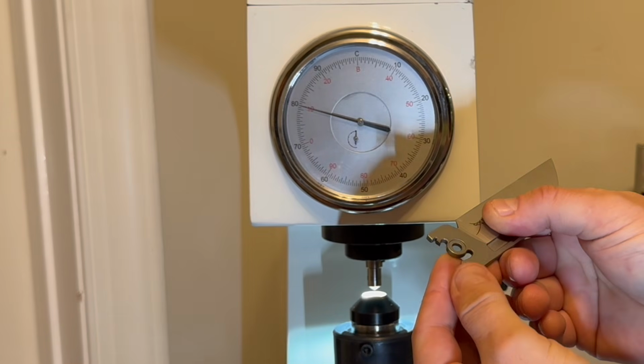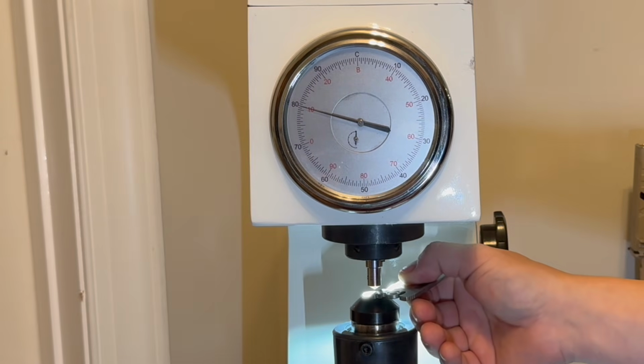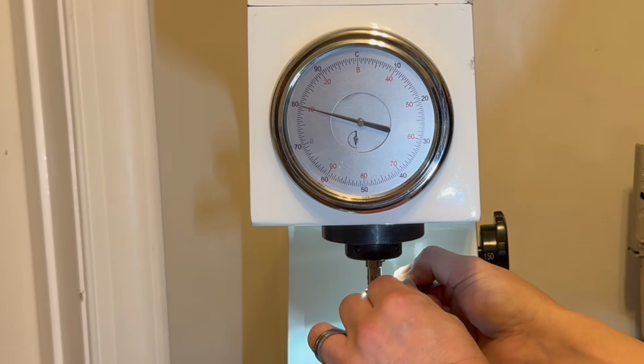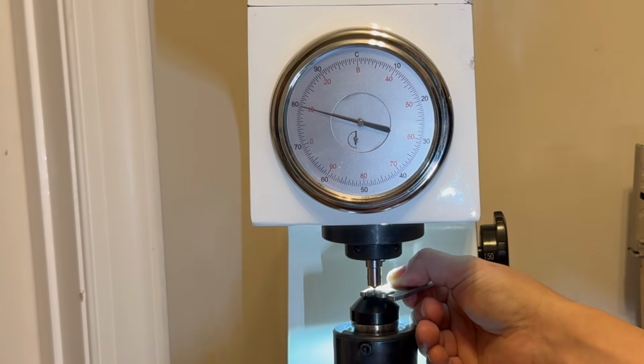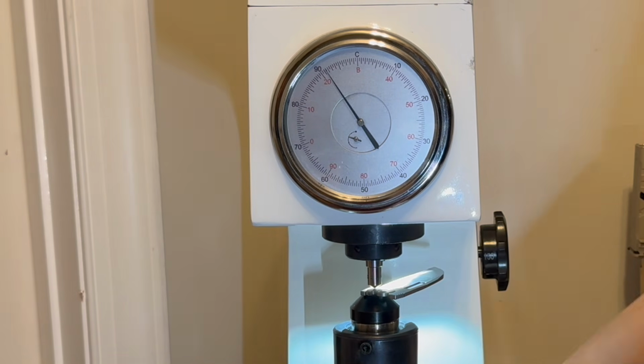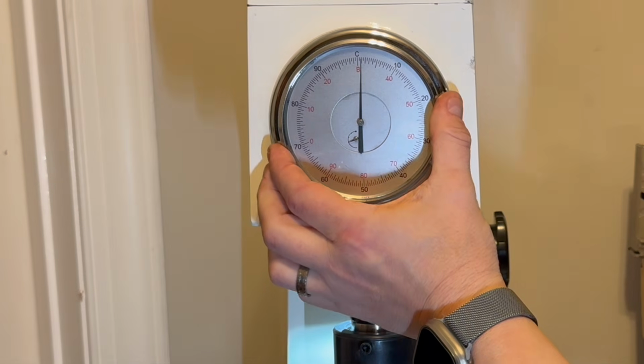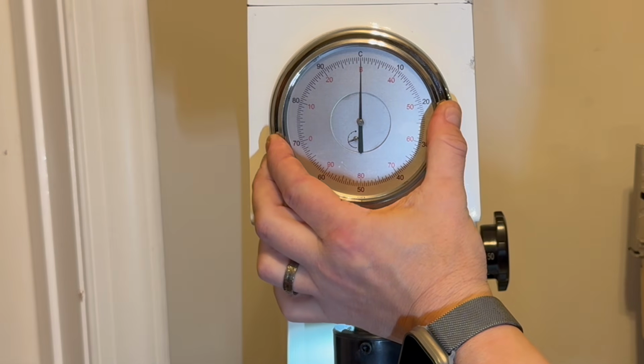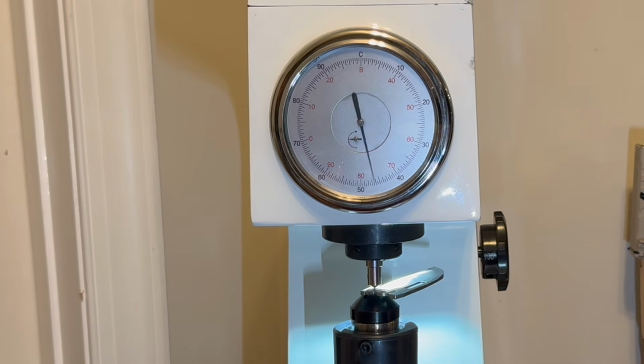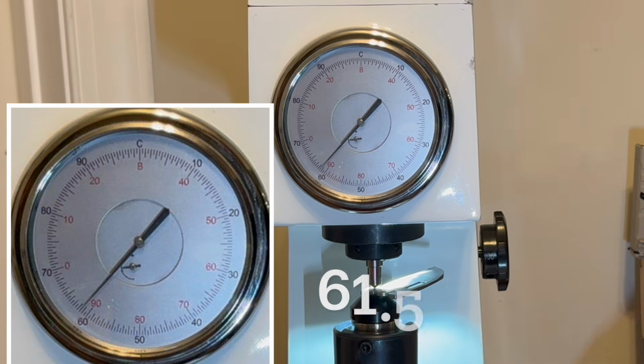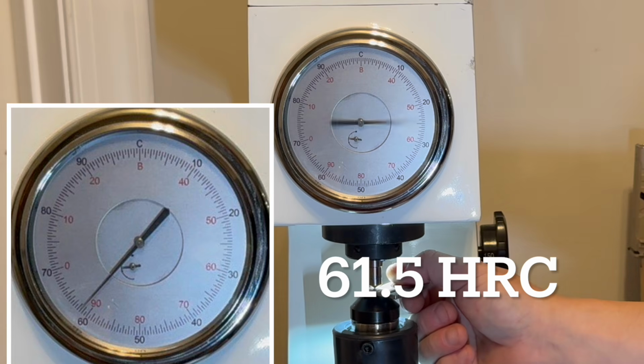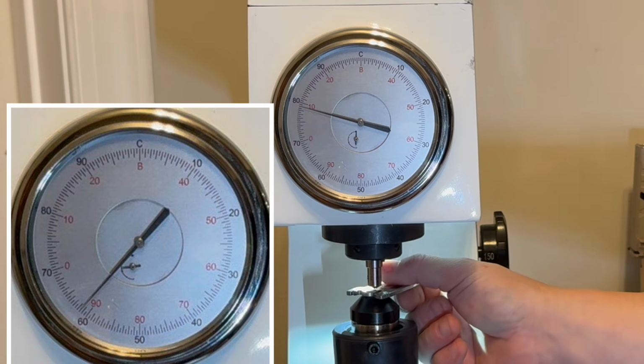61 to 63 is what custom makers select for S45VN. Why, you ask? Because at this hardness, the edge retention will be maximized without much of a reduction in toughness of the blade, and without any noticeable reduction in corrosion resistance. Only a very good manufacturing company would plan their heat treat activities to accommodate the coating. 61.5 HRC on this poke. So we're in the zone there.